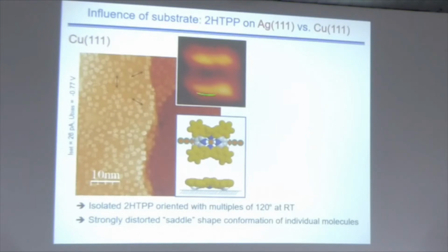This is now the high resolution image. It looks a little different than the saddle-shaped deformation. And then, what is the reason for this orientation? The chemists immediately would say, oh, that's not so surprising, because nitrogen wants to interact, or does interact, strongly with copper. So we form strong copper-nitrogen bonds, and there we bind covalently to the substrate, and that gives you then a very well-defined orientation.